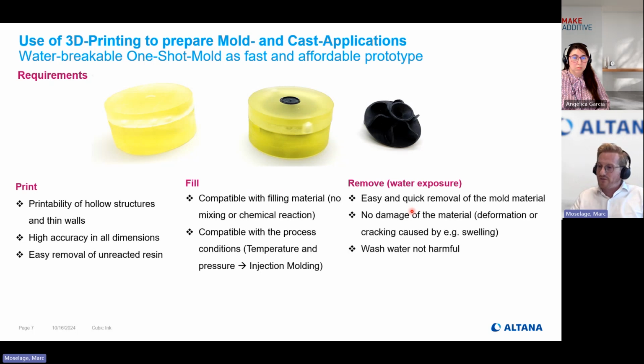Coming to the filling, whatever you fill, could be a 2K material, could be an injection molding material, the mold needs to be compatible with this material. And this implies first a chemical compatibility. The material is not allowed to react with the mold material, and also shouldn't do any sort of mixing, because you can have problems with the surface and also with the accuracy in the end. Chemical compatibility is one point, but also physical. It needs to be compatible with the whole process, and that includes temperature as well as pressure. For example, in injection molding, where temperature and pressure are really high, this new mold, of course, needs to tolerate that.